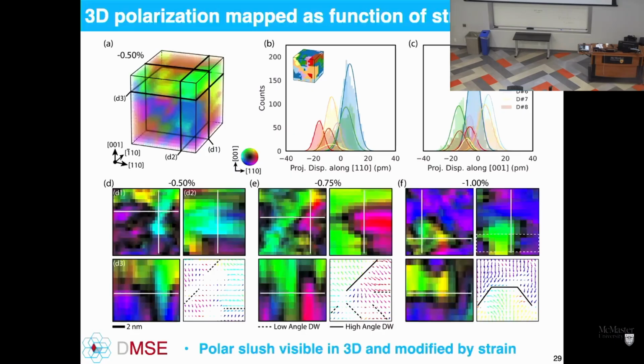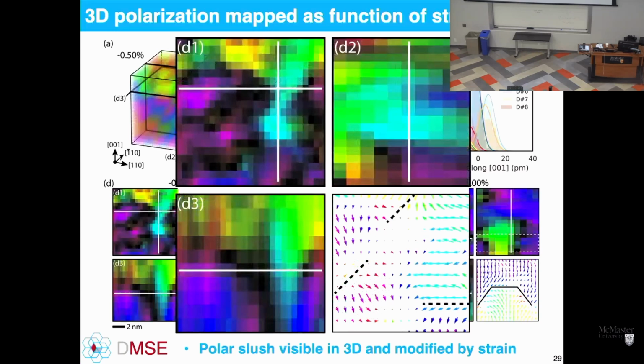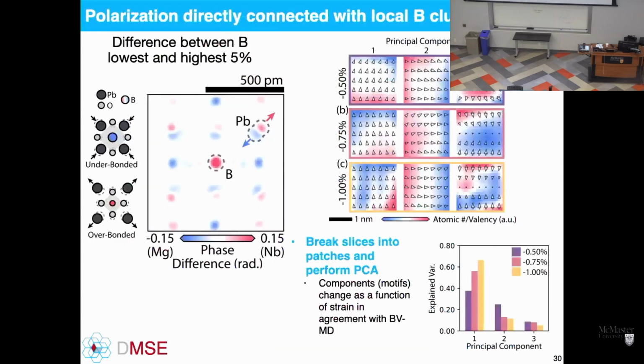What was interesting about this is that that's a high-energy domain wall. If you look at the theory calculations, that was unexpected. You would not expect to actually find that, and I'll show you why in just a second. But again, you start to pull out all this information. You can interrogate what the potential is basically at every point in your image. This would be a template average over a large area.